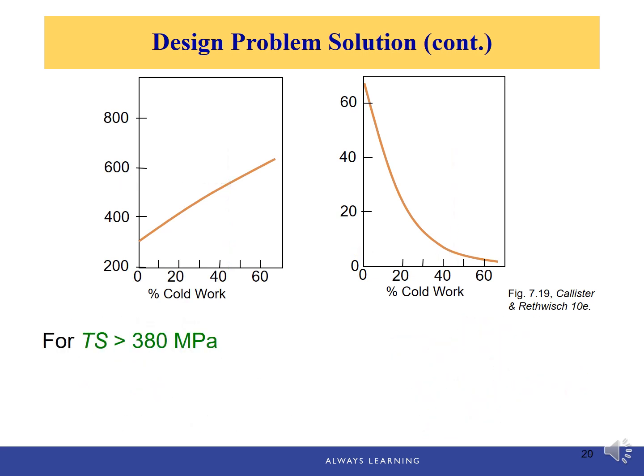Now, let's check for the required tensile strength, which is 380. How much cold work should we do at least? Because the tensile strength increases with the amount of cold work, to reach the minimum value, we need to do at least 12% of cold work to have the desired strength for the material.